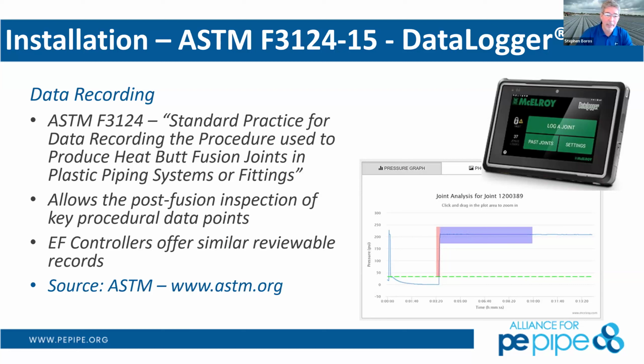And if you can see this, you have a 99% chance that all those joints are going to be good. Now, I say 99% chance because the only thing that could possibly go wrong is if some dirt blew in there or something like that that wasn't taken into account. Then that's the only thing this type of data logger won't record. But everything else, as long as it goes through this process and you record the steps, you can be assured that you're going to have a good, strong joint afterwards.